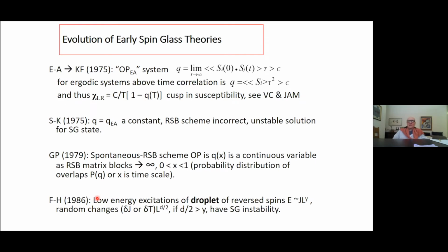As I said, Edwards and Anderson, then working in Cambridge, came up with an order parameter. This order parameter was, first of all, time dependent. I could use this even as a single site order parameter, and look at, as the time goes on to infinity, this spin dot product remains finite. There is no mobility as I look over time. Now, in statistical mechanics, for ergodic systems, I can convert the time correlation function here into a thermal averaging squared function for the order parameter. This is the proposed order parameter of Edwards and Anderson. I need to do a thermal averaging, and I need to do a configurational averaging.